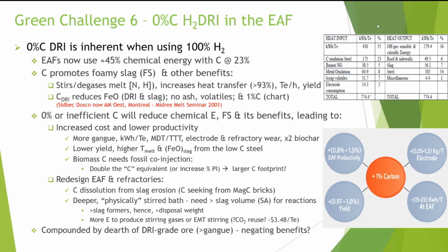But if we have all these scenarios, especially with a higher slag volume involved to give us the quality of liquid steel, we're going to have to redesign the EAF and the refractories to compensate for that, to prevent carbon dissolution from the refractories. And we're going to have a deeper bath. It's going to have to be stirred either electromagnetically or physically. We're going to have more slag formers required and more slag to dispose of, and therefore more cost. And all of this is going to be compounded by the lack of, or dearth of, DRI grade ore.